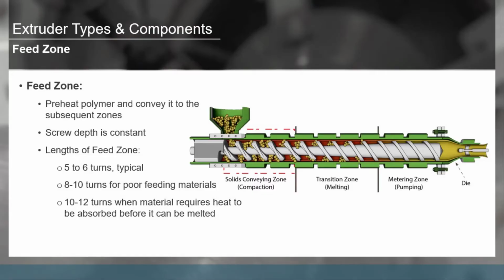So the length of the feed zone is typically 5 to 6 turns, but it may go up to 8 to 10 for poor-feeding materials, or 10 to 12 when materials require heat to absorb before they can be melted.